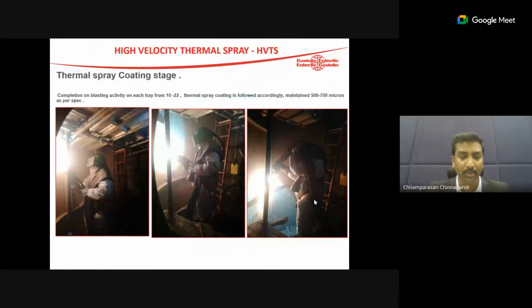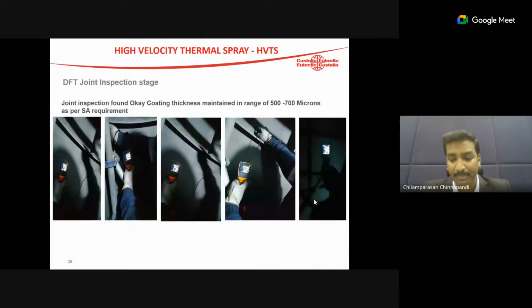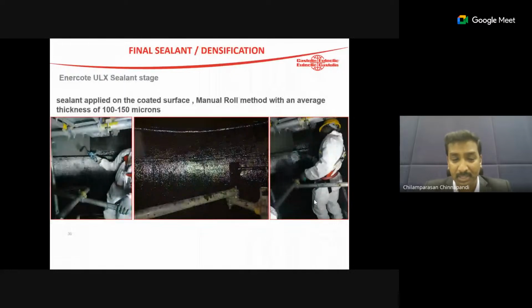And we have done the thermal spray coatings with what we call the high velocity thermal spray, HVTS process, which is sprayed on the vessels so it can avoid corrosion, erosion, all this. But in the HVTS process, or any general process, there will be porosities after the spray, up to 5% to 10%. That has to be sealed before it goes for operations. So we have a specialized high temperature sealant to ensure that all porosities are sealed. We call it densification also. That will be completely sealed.